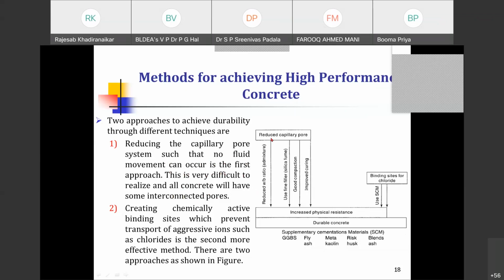So how exactly is that achieved in practice? We need to reduce the capillary pores. First, a reduced water binder ratio. When I reduce the water binder ratio, at least the water voids will come down. Then use of fine fillers like silica fume, wherein even the smallest of the voids will be filled. It also acts as a super filler as well as a super pozzolana. And then there will be good compaction. This is another technique, that you go for better compaction and improved curing. Curing is equally important. So this first technique, reducing the capillary pores, is achieved by these four means.